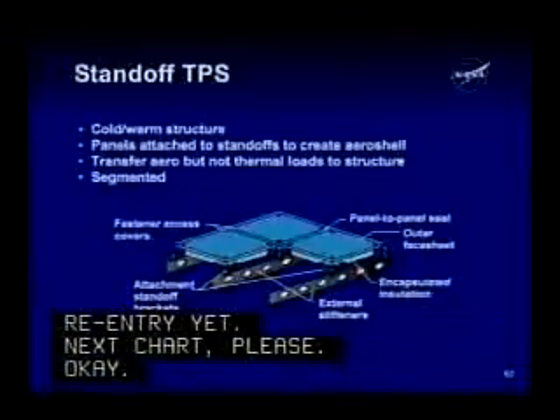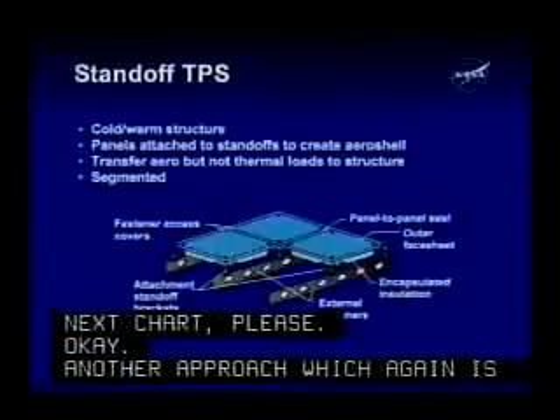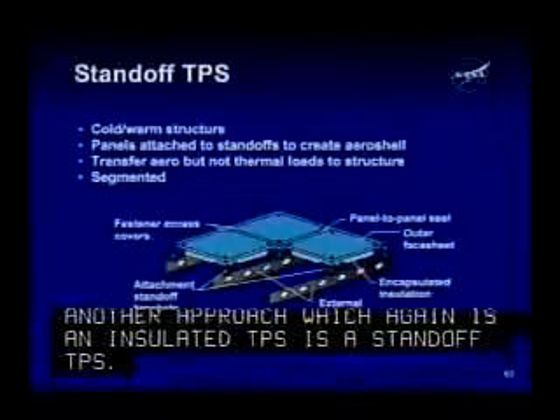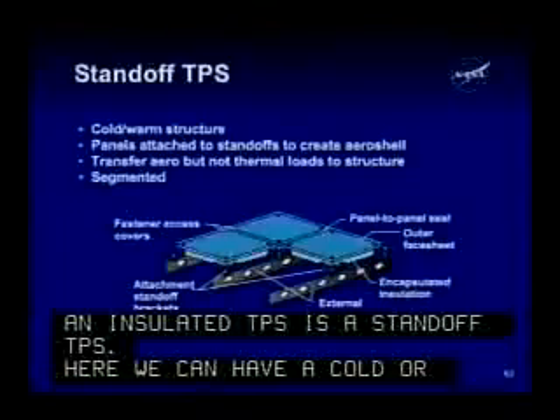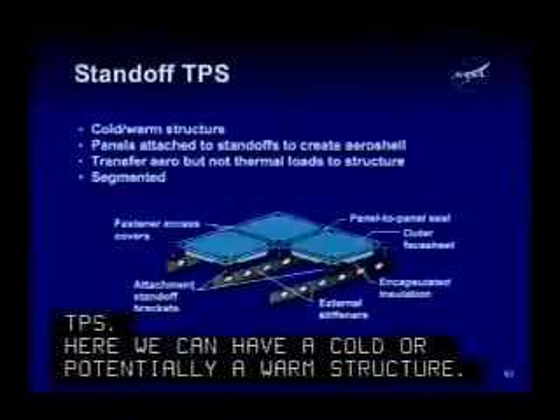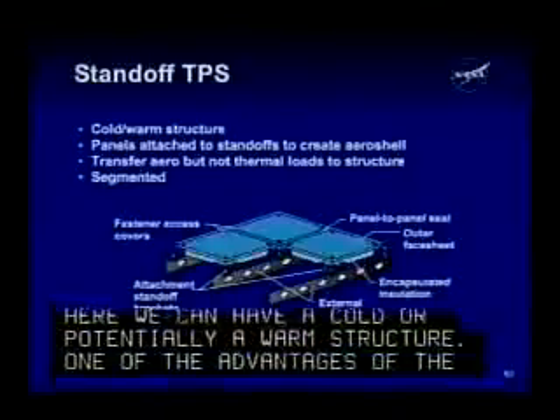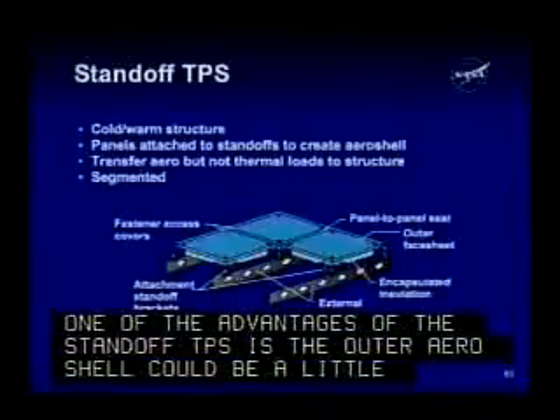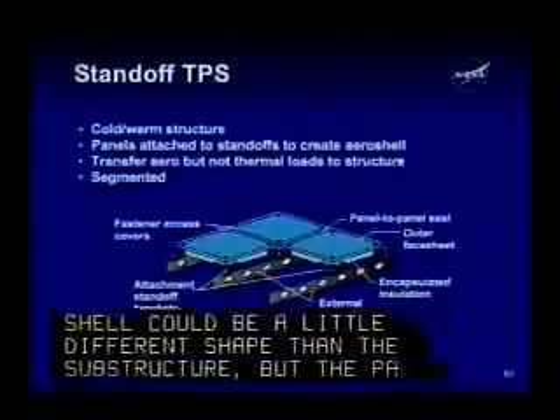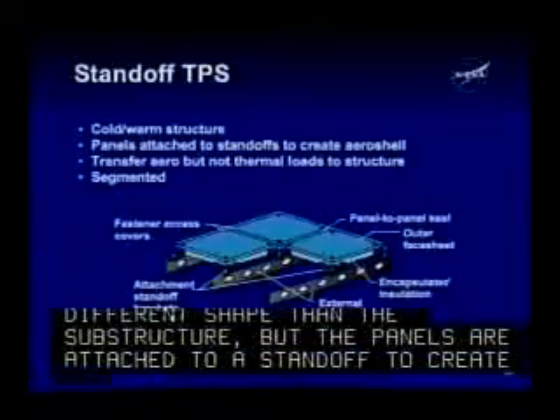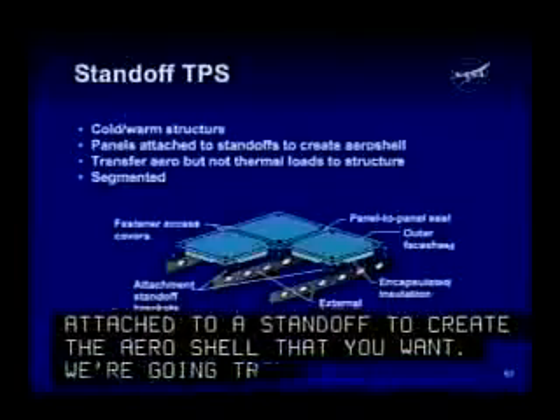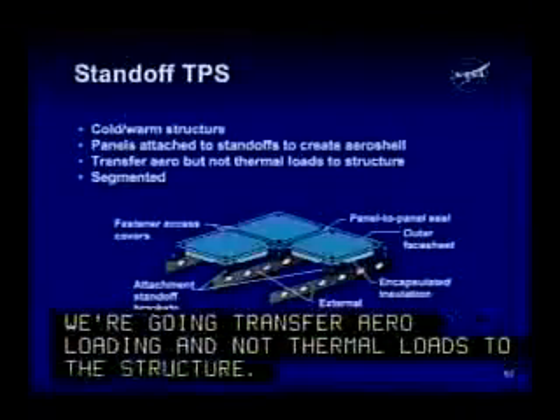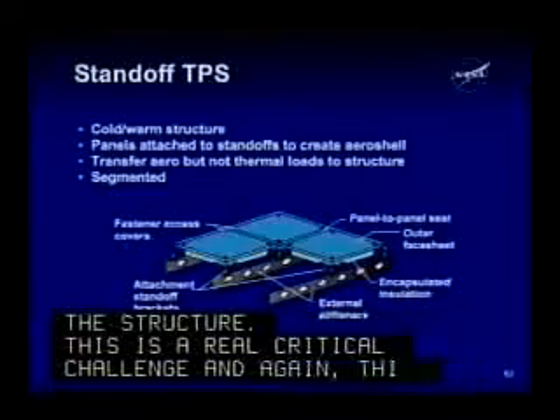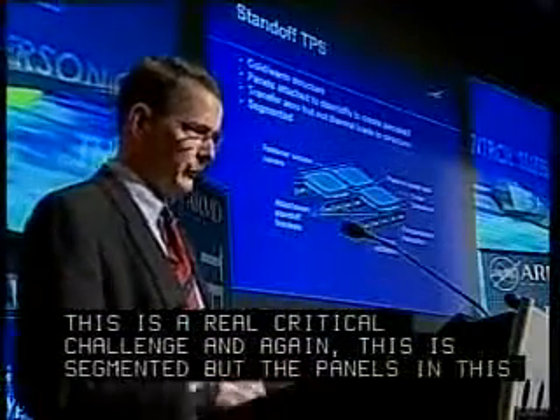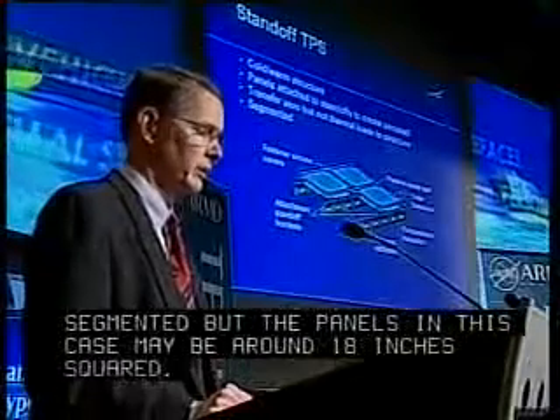Okay, another approach, which again is an insulated TPS, is a standoff TPS. Here we can have a cold or potentially a warm structure. One of the advantages of the standoff TPS is that the outer aeroshell could be a little different shape than the substructure. But the panels are attached to a standoff to create the aeroshell that you want. We're going to transfer aero loads but not thermal loads to the structure. Again, this is a real critical challenge. And again, this is segmented, but the panels in this case may be around 18 inches square. So next chart, please.